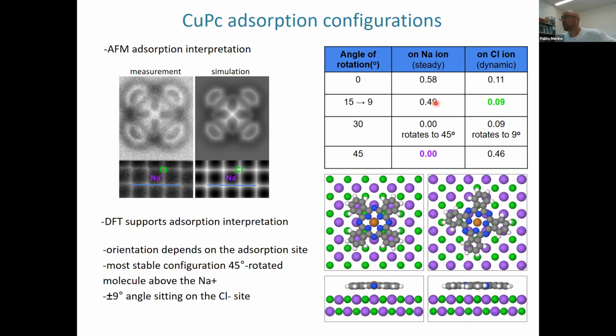So for molecules on sodium, the molecule tends to be at 45 degrees. The minimum energy is found at the molecules rotated 45 degrees, which is this configuration, which is exactly what we see here. And for the molecules sitting on chlorine atoms, what we see is that they tend to go to a rotation of 9 degrees, okay, with a slightly higher energy, but still reasonable. And these are the 2 adsorption configurations that permit the rotation, and then we have the dynamic character.